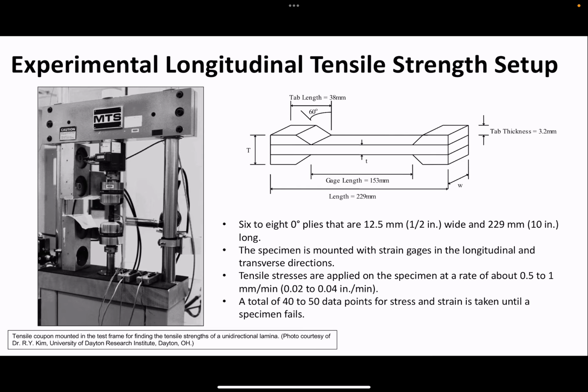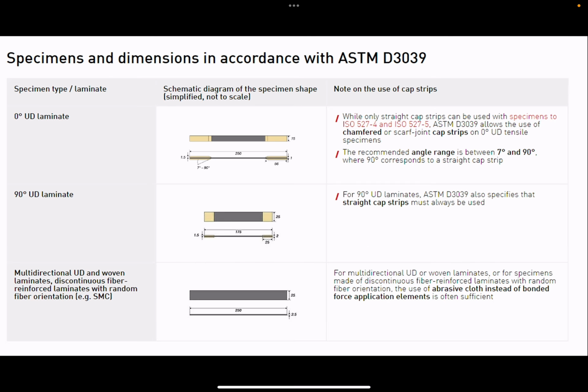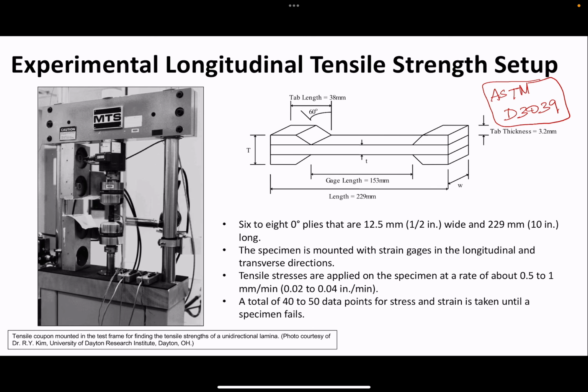Okay, so for first, this is the one we are going to do in class as well. Experimental longitudinal tensile strength. Alright, so here you have done so many tensile tests. I believe that you know this already, but because it is a composite, the standards are different. Here we follow the ASTM standard D3039. So it states that you have to use 6 to 8 0-degree plies that are 1/2 inch wide and 10 inches long.